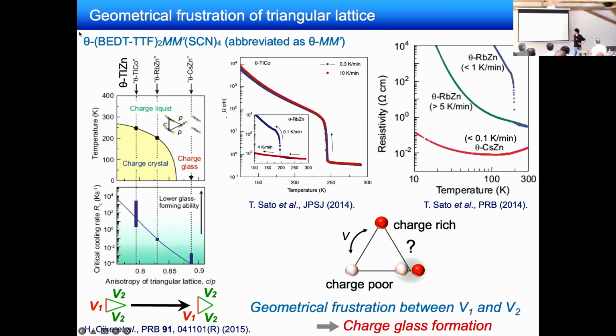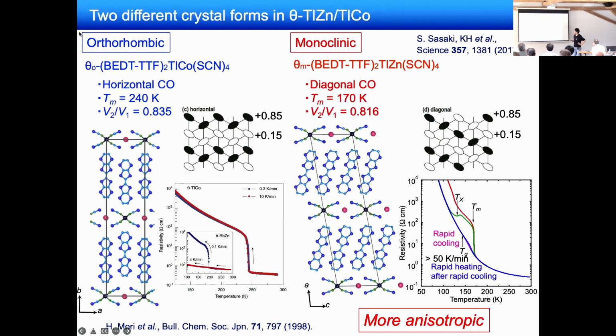Okay, so in this presentation, I will focus on the theta-thallium zinc compound, which has the most anisotropic triangular lattice. In the theta-thallium zinc compound, there are two different crystal forms with orthorhombic and monoclinic symmetries. And the orthorhombic one shows a horizontal charge order at 240 Kelvin, like this.